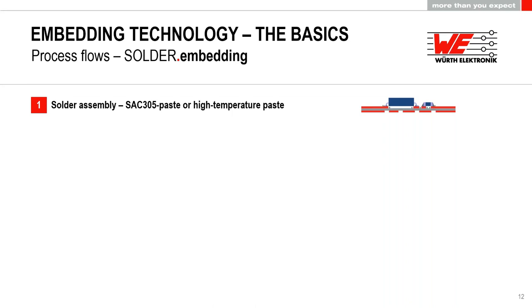This modification is basically two points. We have a very small solder resist system introduced here, which means we only create a frame surrounding the solder pads so that this functionality of the solder mask is kept, so that the solder in the reflow process doesn't flow away onto the tracks and something like this.